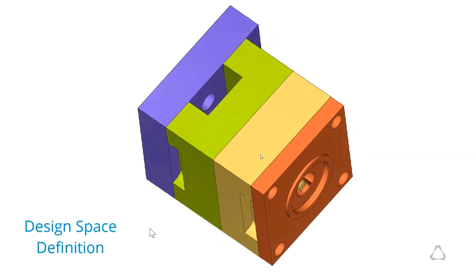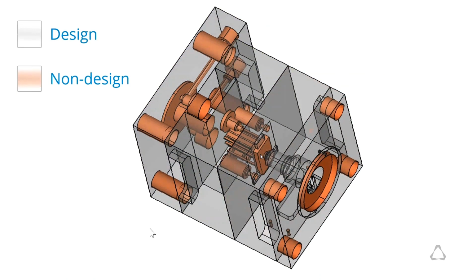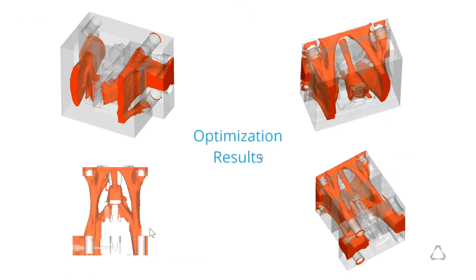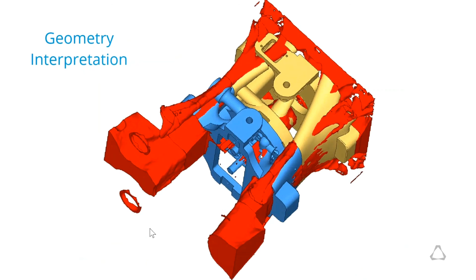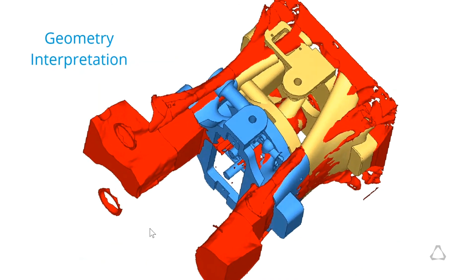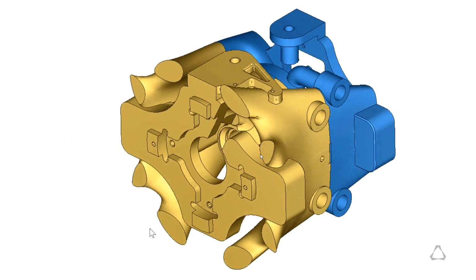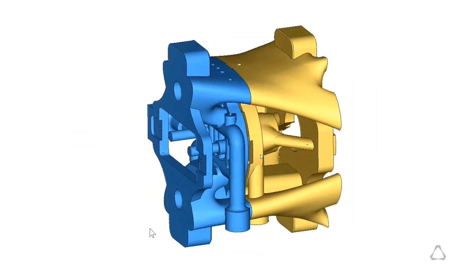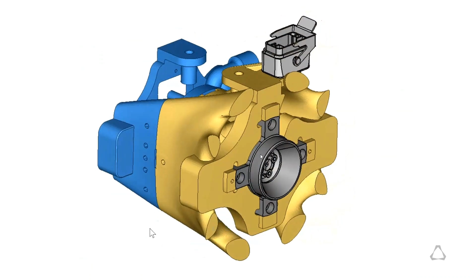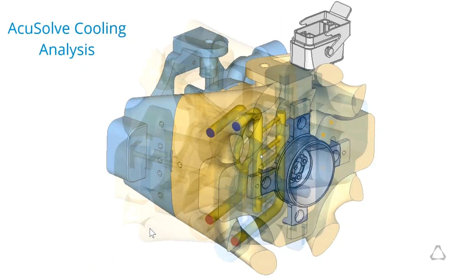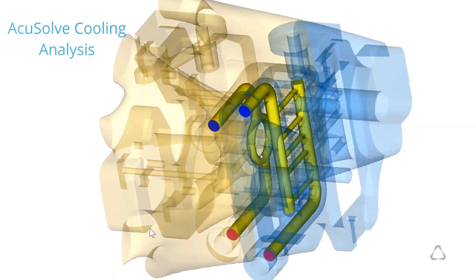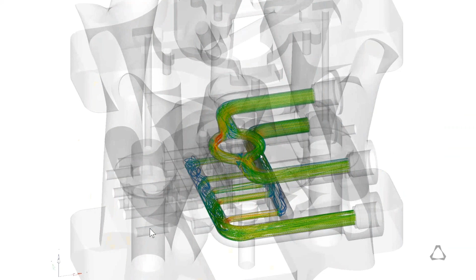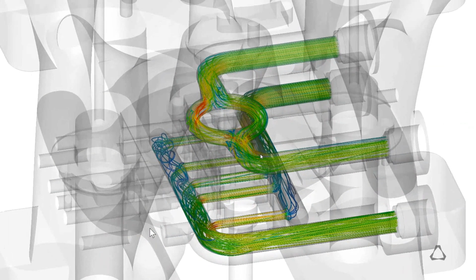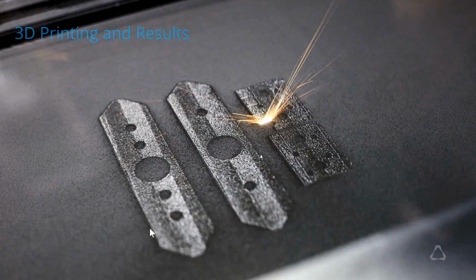So again, the same concept. You define a design space and you define a non-design space, and you optimize it the same way. You come up with a bionic structure. And in this case, in addition to that, we also looked at the thermal side of it as well, where we ran AcuSolve, which is the CFD solver within the Altair portfolio, to make sure that the heat dissipation is also extremely efficient. So not only did we optimize it structurally, but we also optimized the heat dissipation, and the whole die in this case was 3D printed.